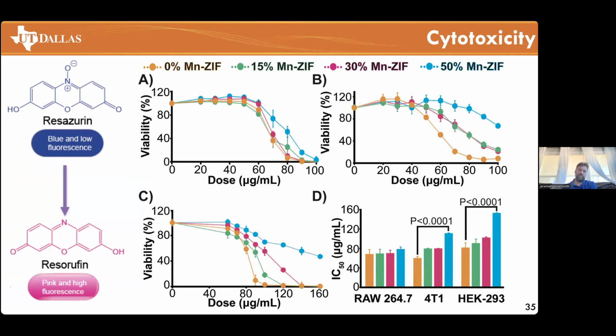Cytotoxicity: if we look at the combined metal organic frameworks, and I should mention this because cytotoxicity is often brought up, the metal organic frameworks that contain zinc, so ZIF-8, are less cytotoxic than alum by a small amount, not large. Alum is already used in vaccines. The dose that we use is typically around 20 micrograms per milliliter, so well below the cytotoxic dose. And this just points out in this particular case that the mixed manganese ZIF is slightly less toxic than pure zinc, presumably because the reactive oxygen species that the zinc probably produces is mitigated by the manganese in sort of a SOD-like reduction pathway.